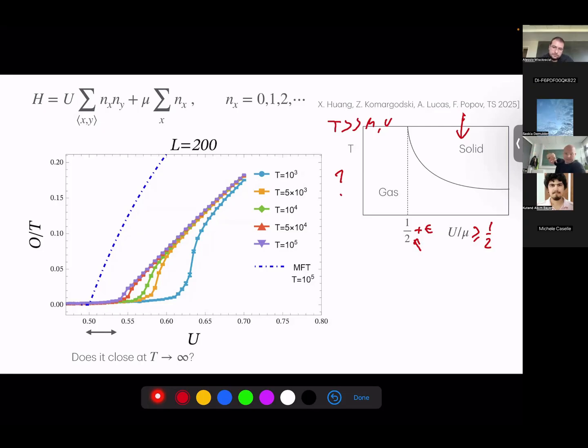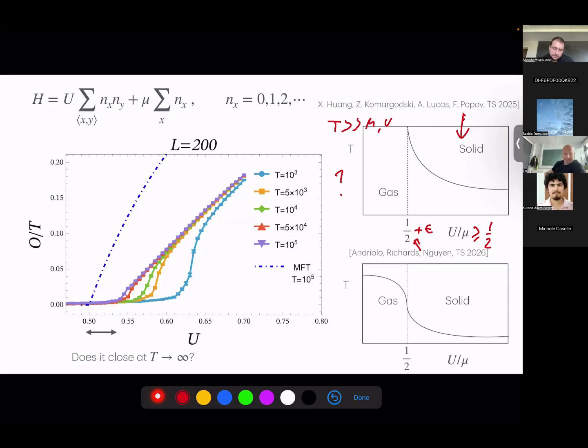And in the most recent paper, now this I will just say without saying why this is so, because it would take me too far afield. In the most recent paper with my postdocs and students, we actually proved entropic order of this model. And we managed to prove it for U sufficiently large. We don't know exactly how large it has to be, but it's some finite but large U. However, this proof also seems to strongly indicate, although it's not a proof anymore, that maybe the phase diagram of this kind is actually true, that a solid at very high temperature persists for all values of U. But for very small values of U, the transition temperature is very large. Now, we don't know how to prove this.